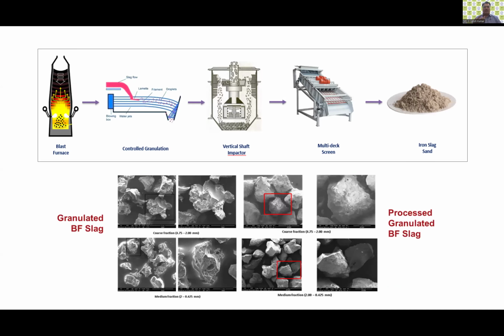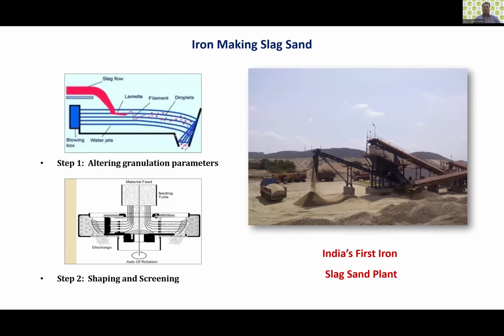We utilized a vertical shaft impactor and a multi-deck screen, and finally what came out was a processed granulated blast furnace slag from a granulated blast furnace slag. And you can see in these pictures how the shape and morphology has changed from a very irregular, highly porous structure to more uniform and rounded pieces, which resemble the iron making slag more closely. And once it was compared, we found that this processed granulated blast furnace slag could be a 100% replacement for the river sand which is being used in the construction industry.